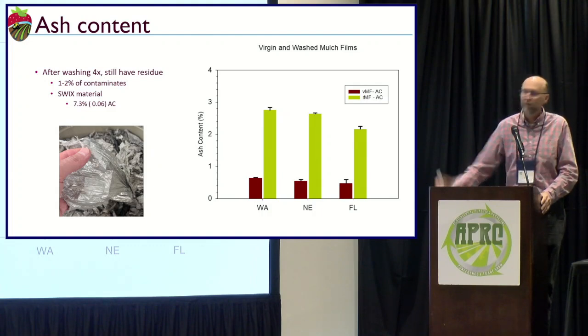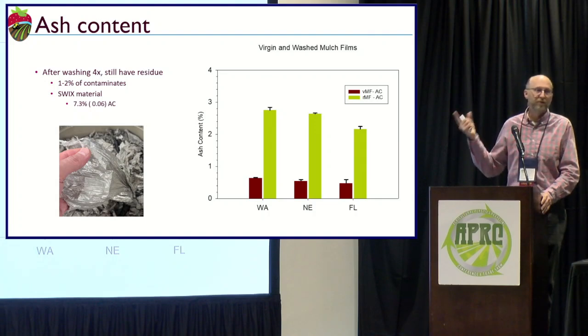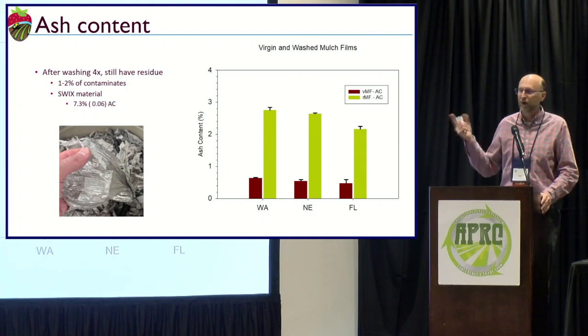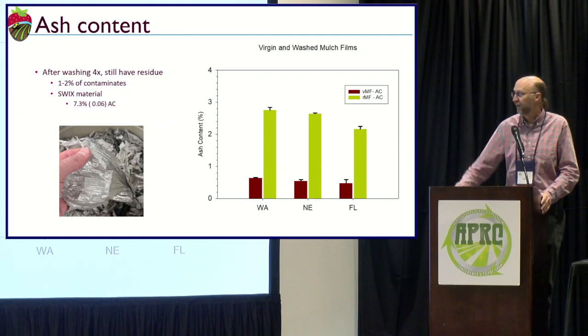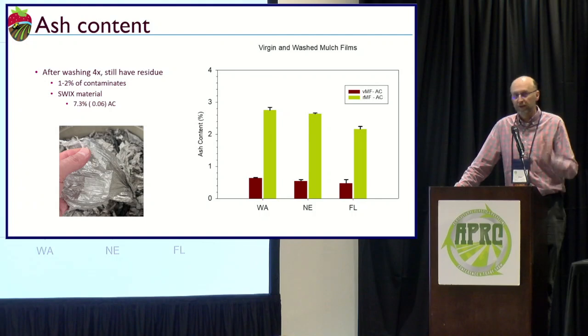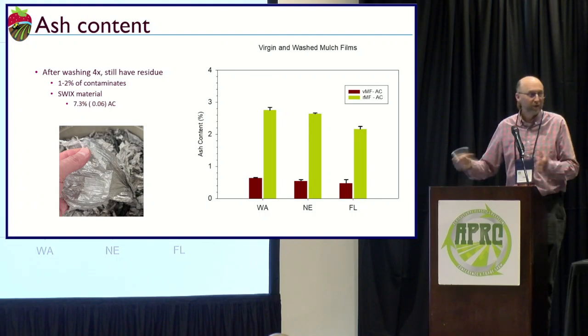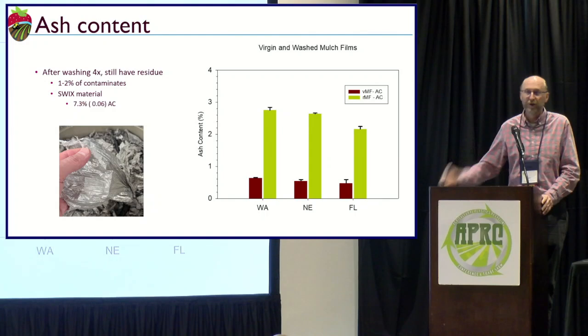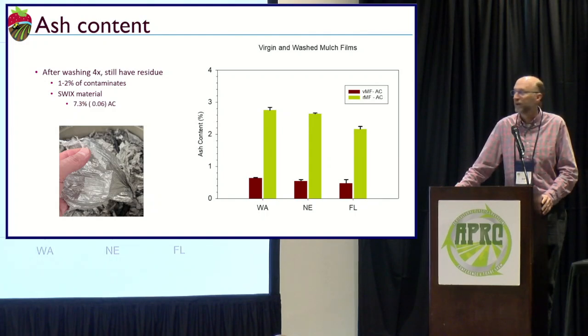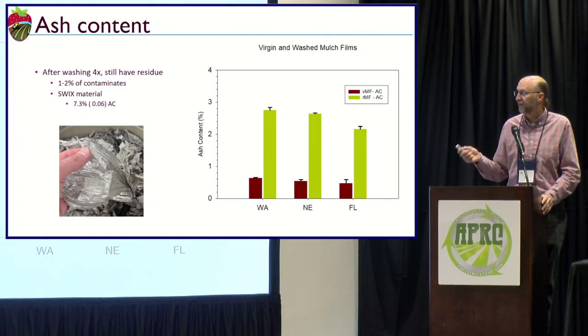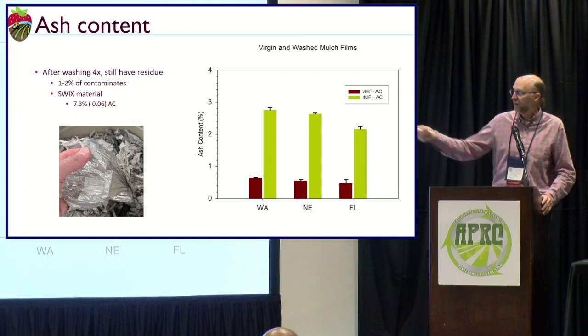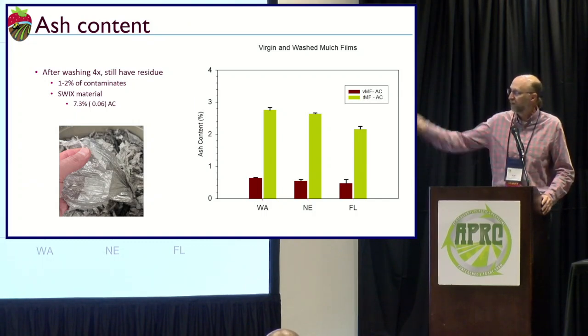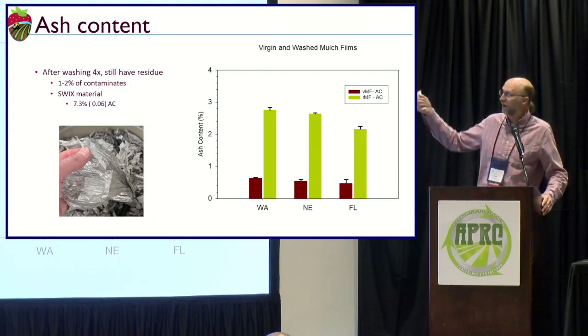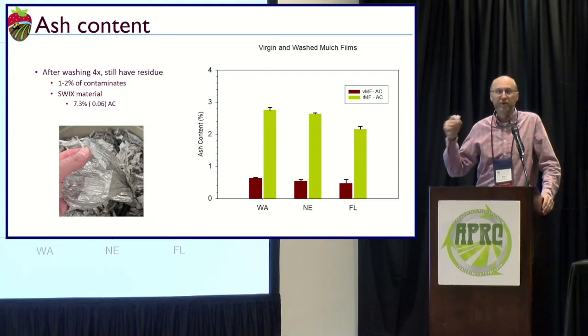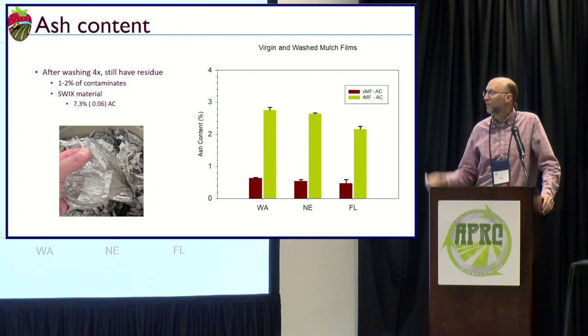But you can still see, even after 4 washes, we still have some soil or contaminant load on there. We're up around 3%, maybe down to 2.1 with the Florida material. It may look clean and your wash water may be clean, but you're still always going to have a little bit of soil on there. That's something you need to take into consideration. The other thing is the Swix material, which I didn't put on the graph, came up to about a 7.3, so it's quite a bit higher, mainly because of the aluminum that was on the surface.